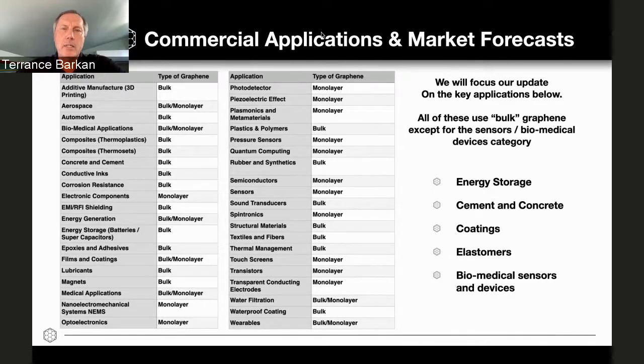The areas where graphene is getting a lot of traction commercially right now, energy storage, so battery technology and chemistries, surprisingly cement and concrete, because when you add graphene to concrete, you can increase its strength, but equally important from a commercial perspective, you can reduce the cure time, so you get to the target strength rate in 7 days instead of 28 days, for example. So that has huge economic implications. Coatings, elastomers, and then on the sensing technology, especially for biomedical sensors, so looking for new biomedical sensing that is much more sensitive, much more selective, much faster, and has a smaller footprint, for example. So again, if you compare medical sensors with concrete, you couldn't be more diverse.